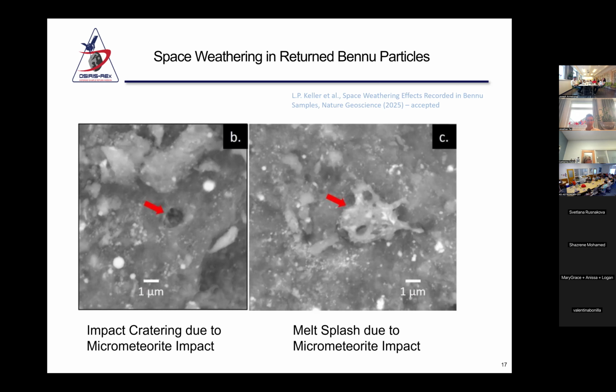So that's a great question. Presumably, it could be pressure, right? So you could have, perhaps in the parent body, there is some compression. It could be also temperature. As it moves around the sun, you heat, you cool, and you create fracture surfaces, and eventually it fractures. Or it could be, you have an impact at the surface, and it propagates the shock down through the surface, creating cracks or fissures, etc. And that rock eventually populates the surface. That would be my best guess.